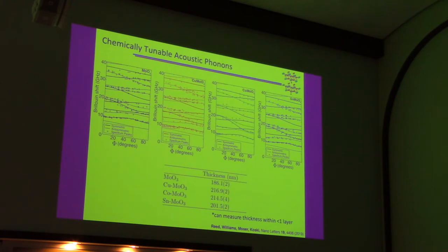Because we're using a Lamb wave solver, we can also extract the thicknesses. I mentioned that by eye, I chose crystals that were nearly all 200 nanometers. Here are the actual thicknesses of these, and we can measure the thickness within less than one layer in addition to all of the elastic stiffness tensors.